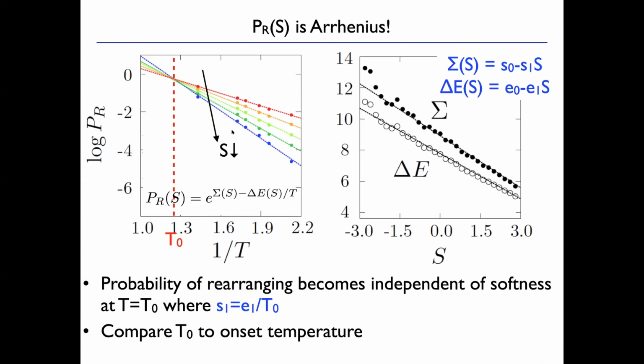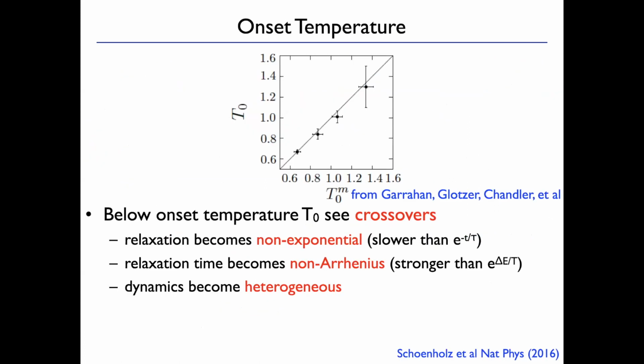And if I look at that, I see, yeah, there is a place where all these curves cross. That's where the probability of rearranging doesn't depend on the softness, okay? I'm going to call that the onset temperature. That's E1 over S1, okay? And I'm going to compare that to the onset temperature that people have measured, for example, when the energy barrier starts to increase. The things where I showed it was constant at first and then started to increase below the onset temperature, or get it from the kinetic heterogeneities.